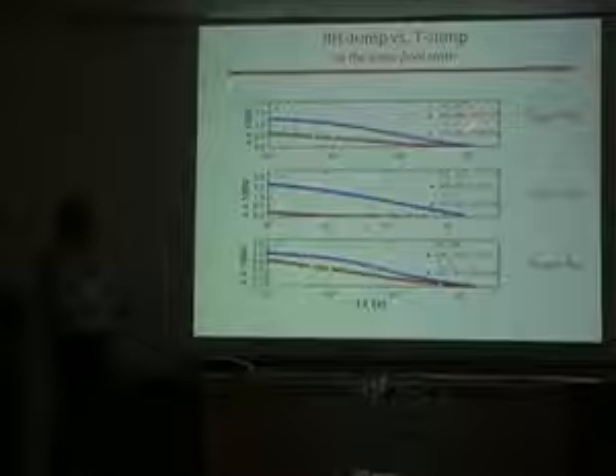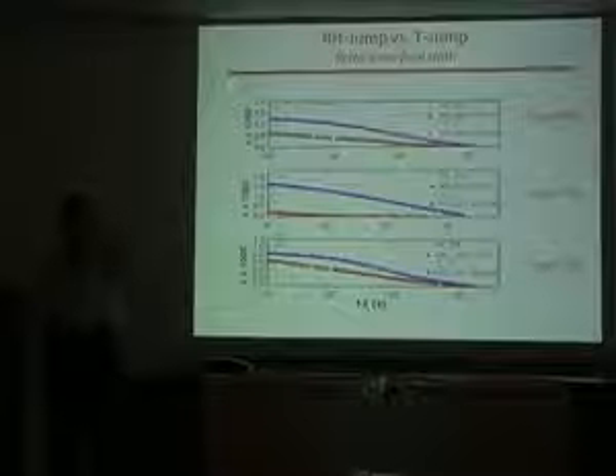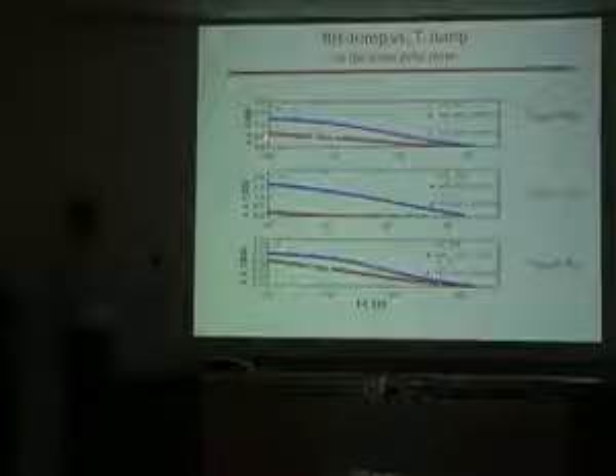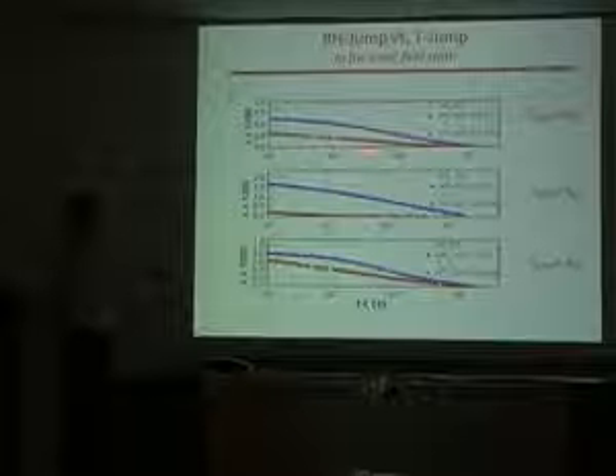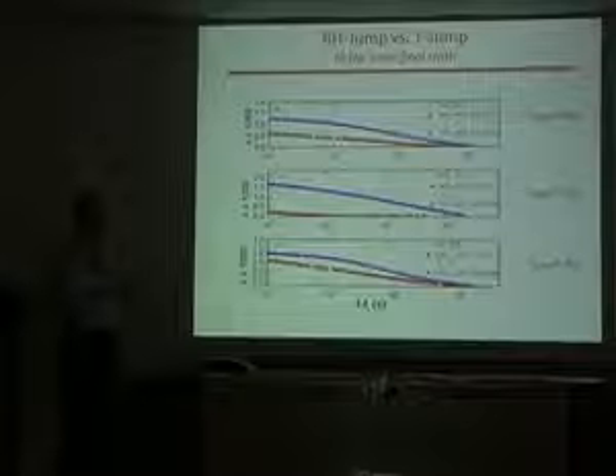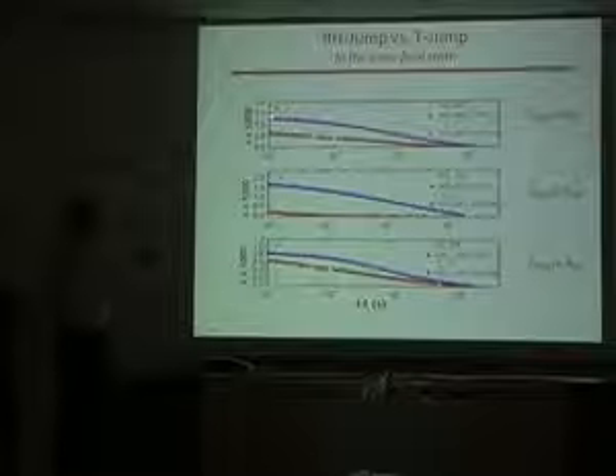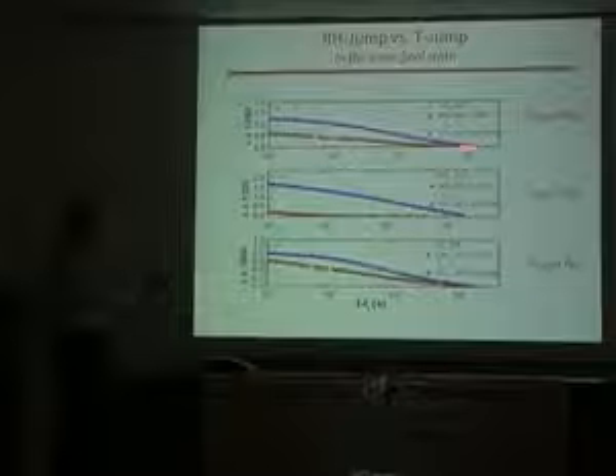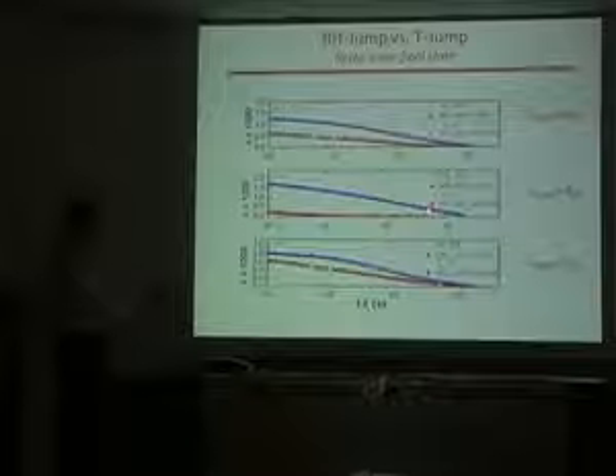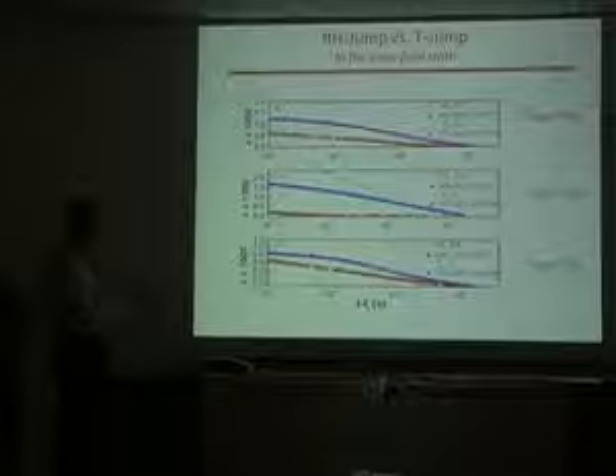So we have the same final relative humidity, same final temperature. So the final external variables are the same. And yet, here's the temperature jump. Not only do we have a smaller volume departure from equilibrium, but we also have a faster relaxation into equilibrium. And here's the humidity jump. It seems to have a much longer time, maybe up to a decade. Here it's even more than a decade in this case, for the volume recovery into equilibrium.